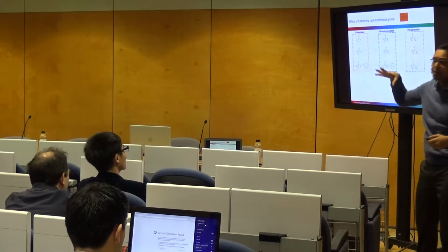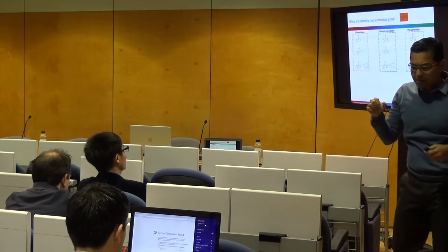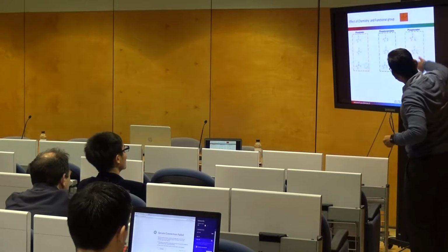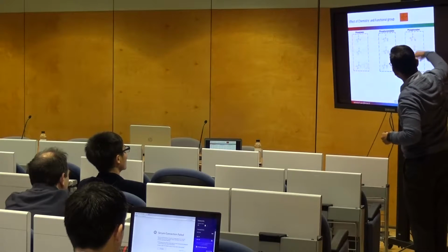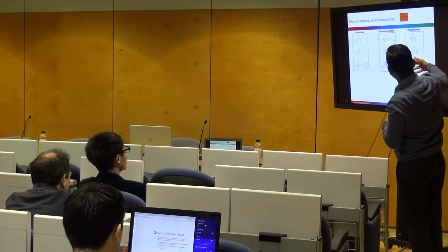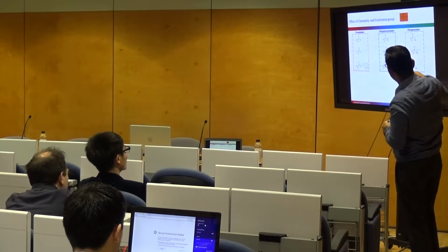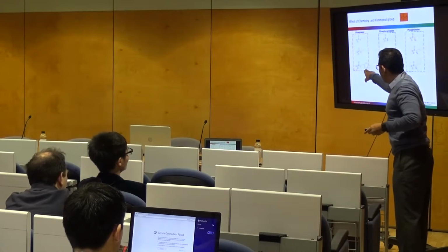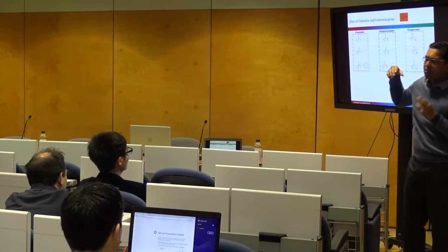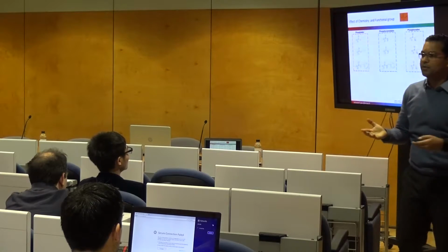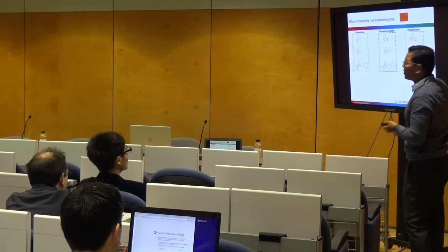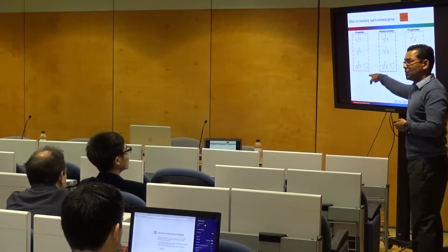Okay, so there are 3 different groups, and by trying to change the substituent on the phosphorus, we are able to design or understand its flame retardancy or tune the flame retardancy. So what we found out in the project: these guys here, phosphates, are probably the worst flame retardant for polyurethane foams. And then we found out these phosphoramidates and phosphonates are better than the phosphates.